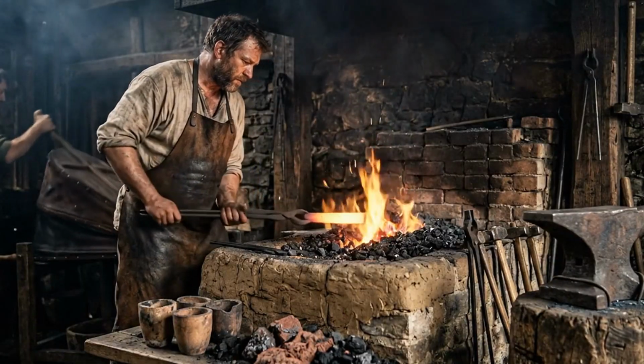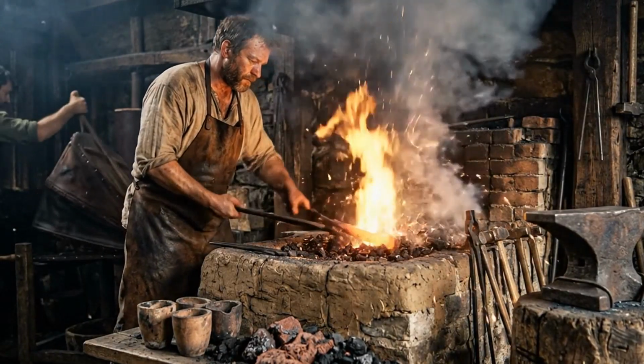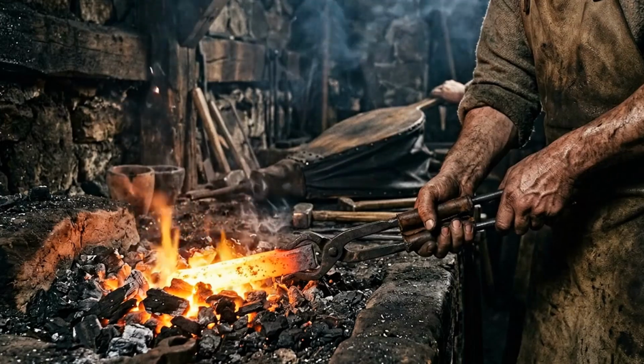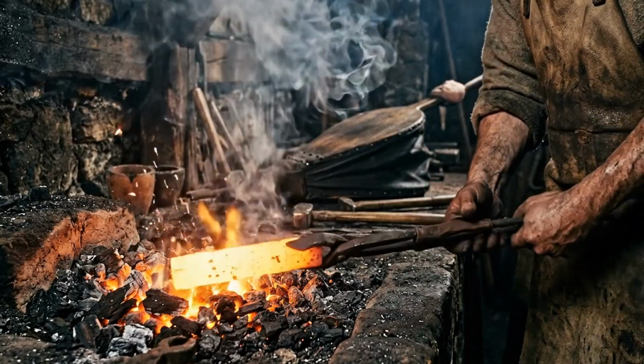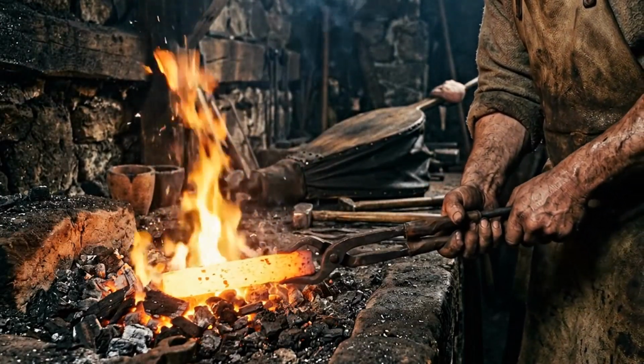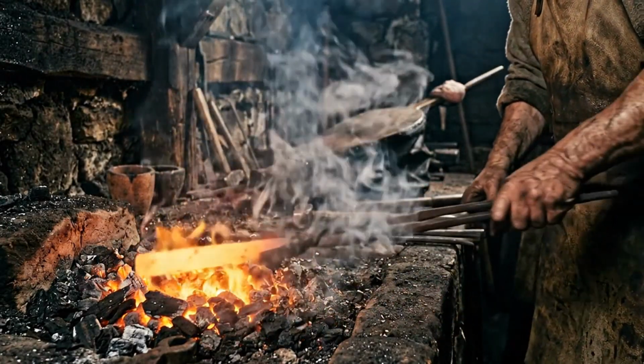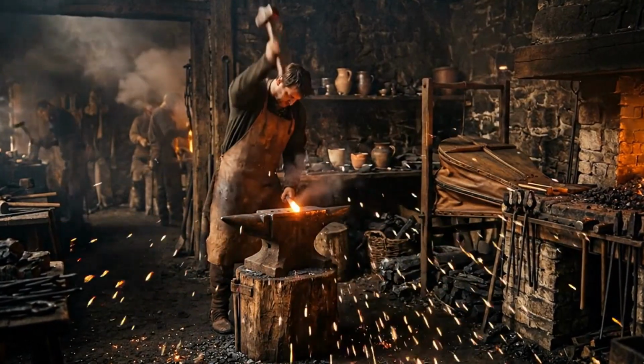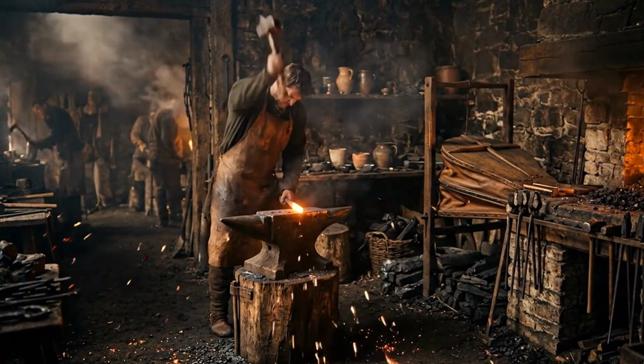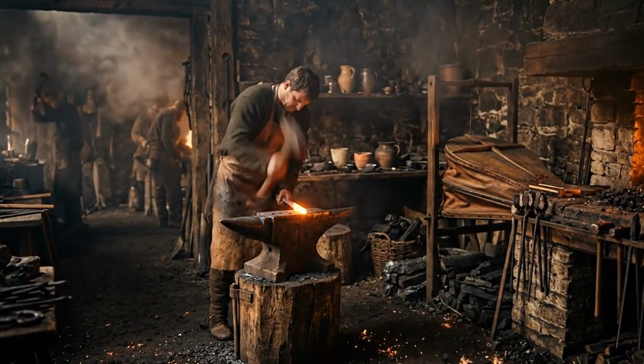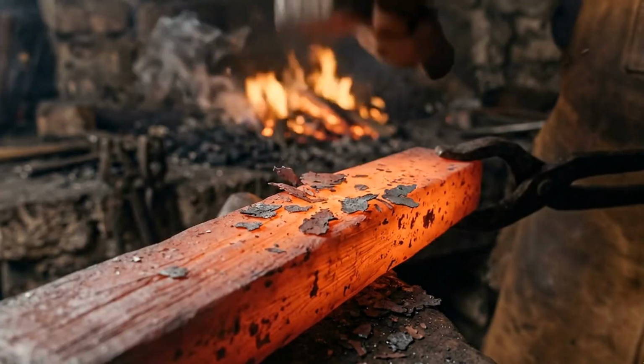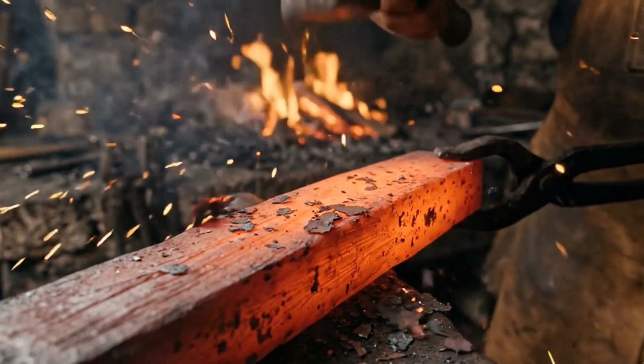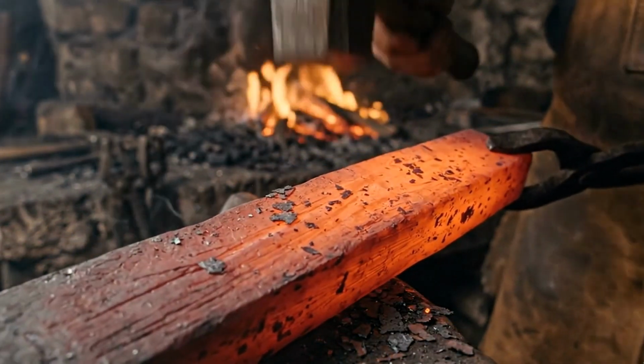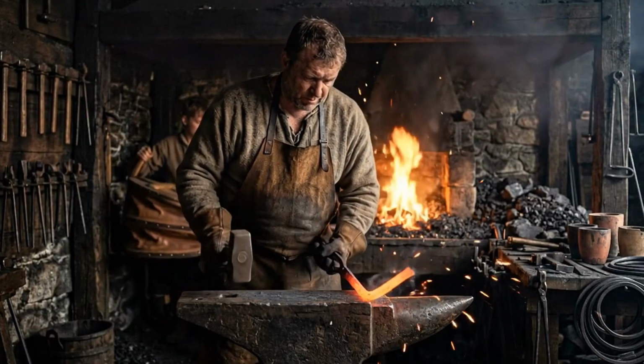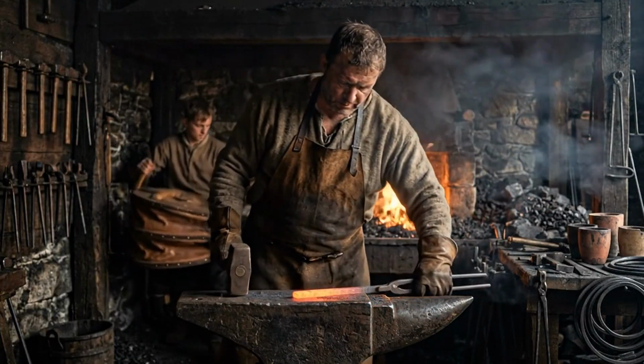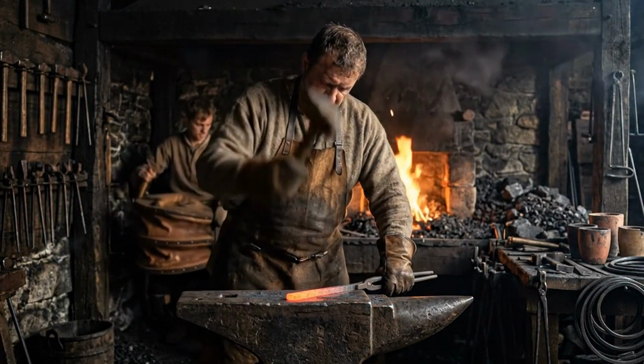The purpose of this process was not to create layers for their own sake. It was to homogenize the carbon content throughout the steel, to eliminate gross variations in hardness, and to work out the remaining slag inclusions that would otherwise create points of weakness in the finished blade. The repeated hammer work also aligned the grain of the steel along the length of the bar, improving its ability to flex without fracturing. The folding process had a critical upper limit.